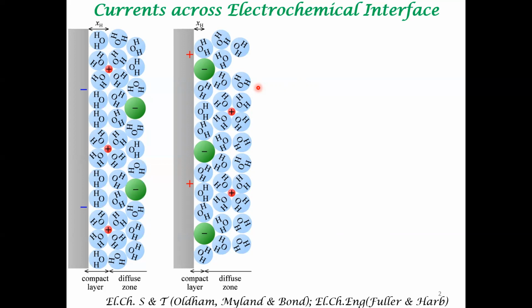We began this course looking at structures like this. If the electrode is polarized cathodically, we interpreted that to mean that the electrode is being charged negatively. Because it's a metallic structure, all the charges are at the surface of the metal. In response to this cathodic polarization, or negative charge at the surface, positive charges in the electrolyte get preferentially adsorbed onto the electrode surface. In contrast, if the electrode is anodically polarized, then there is an accumulation of positive charge at the electrode surface. In response to this, there's a preferential adsorption of negative charges from the electrolyte onto the electrode surface.